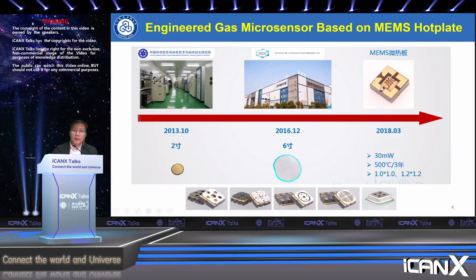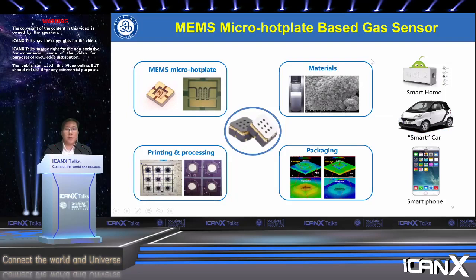And then in the center, there's a 5 micrometer thick floating membrane with the heating electrode and also the sensing electrode. We started this project on 2-inch wafers in our facilities. After 3 years, we moved our design to the foundry to start to scale up the manufacturing. Then we collaborated with our industrial partners, and in about 1.5 years, we got the real product. It's really a long and also iterative process.